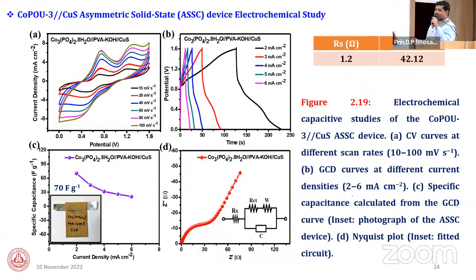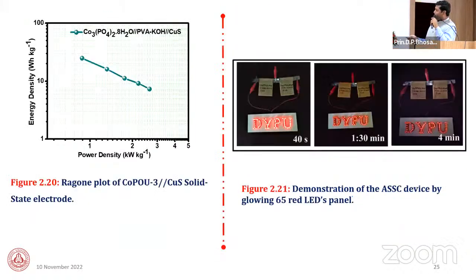But the specific capacity is a little bit less because of the PVA gel, like PVA is a little bit resistive, that's why the performance is a little bit less, and the performance is 70 farad per gram at a 2 milliampere per centimeter square current density. Then this is the energy and power density of this device, and it is 25 watt hour per kg at 0.9 kilowatt per kg. It means 900 watt per kg.